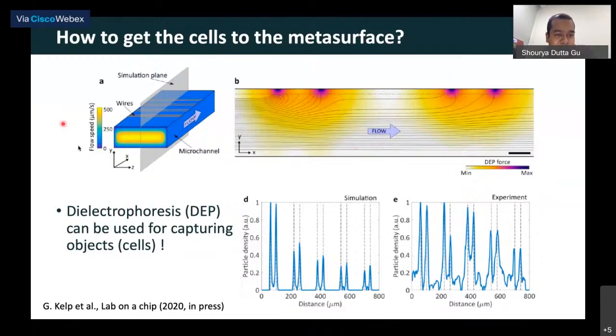So this is the typical channel that we have, and the color here shows you the flow velocity. We have a laminar flow because the Reynolds number is very low, right? And if you look at the cross section shown here, the color represents the DEP force. If you have a blackish purplish color, you have very high force. However, if you have a white or yellowish background, the forces are very small. And the lines that you see correspond to the trajectories followed by the particles, or the cells.